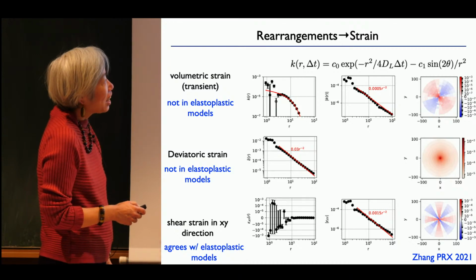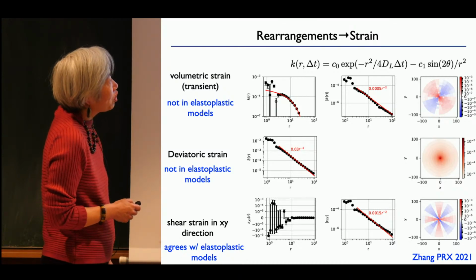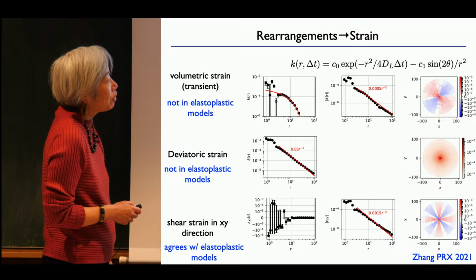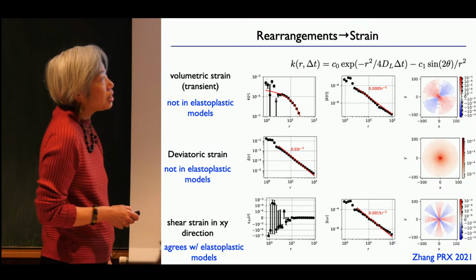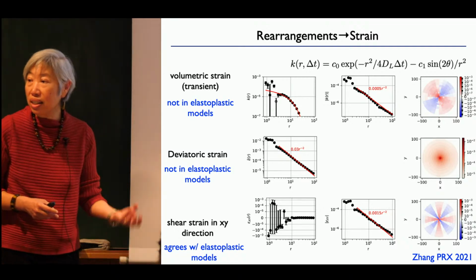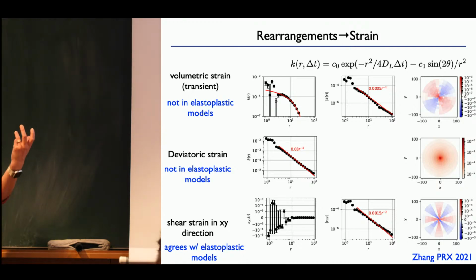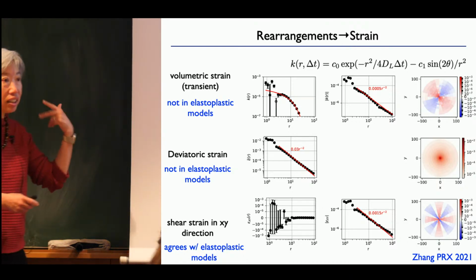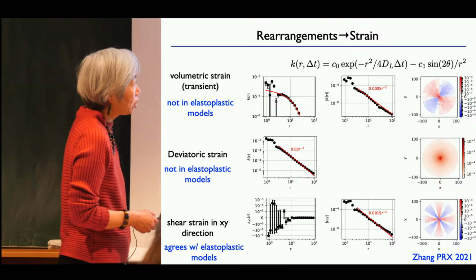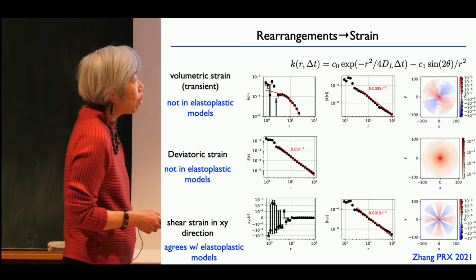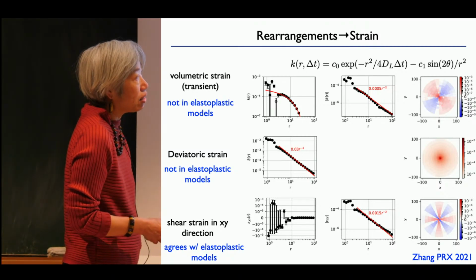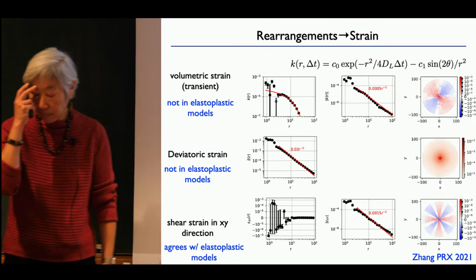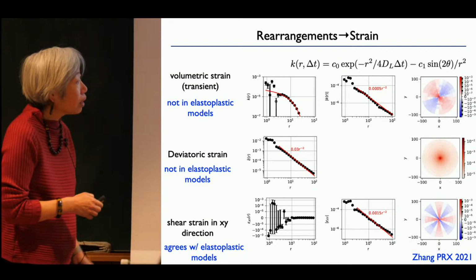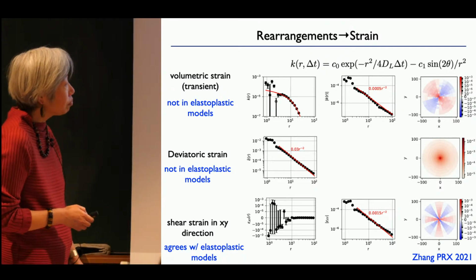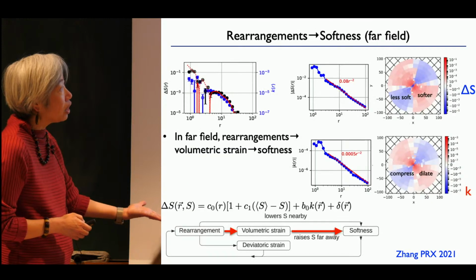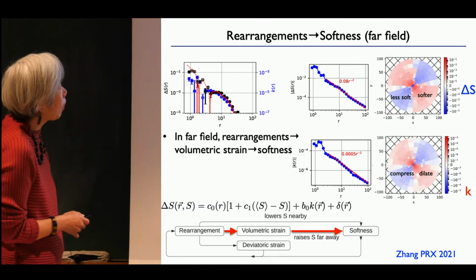All right, so it has this form. The deviatoric strain, okay, is 1 over r squared as well. It is isotropic, right, because this is just the deviatoric component of the strain. All the angles are averaged over, it has to be. And then there's shear strain in the xy direction, 1 over r squared, which has this characteristic quadrupolar form. All right, so by looking at this, then we can look at the change of softness, okay?